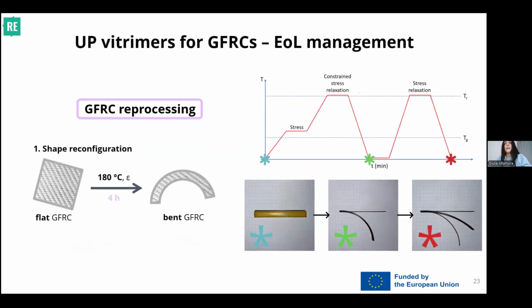Also in this case, I can have you have a look at the thermomechanical cycle that we applied to our materials. So basically, we heat the material up above its Tg to deform it, and then we keep it at the relaxation time in the constrained configuration. So we keep it constrained, we allow the material to relax, then we cool it down, and then we repeat this process, this time without constraint, so that in the last step we have an elastic recovery. And we can end up in the final step, the red dot, with a material that is plastically deformed. So we have no longer temporary elastic deformation in it.